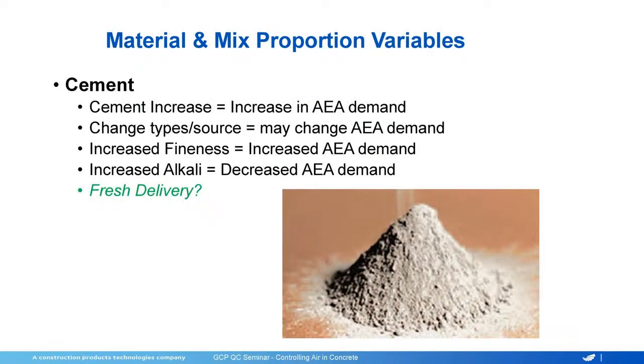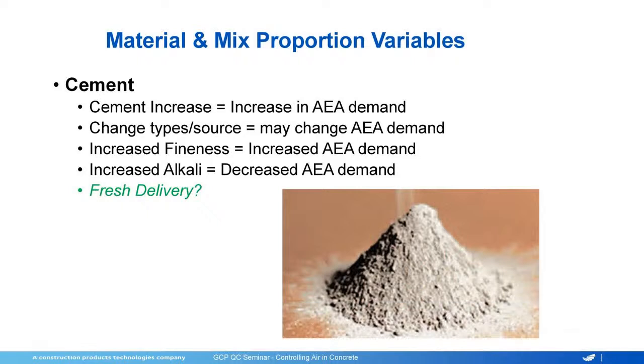If someone asks me what in the mix affects air, and I'm sure if you've been in the concrete industry more than a minute, you know that everything, literally everything in the mix can affect the air entrainment. So if you go up on the cement content, you likely will need to increase your air entraining agent. If you change the source, you're likely going to need to adjust your air entraining agent. If you increase the fineness, you will likely need more air entrainment. One thing we saw with some of the Type IL cements is as they switched from Type I/II to IL, they got finer. So the fineness went up. A lot of that was the limestone portion being fine, but still we saw that it was a bit more difficult to get air in some of those cases because of the fineness.